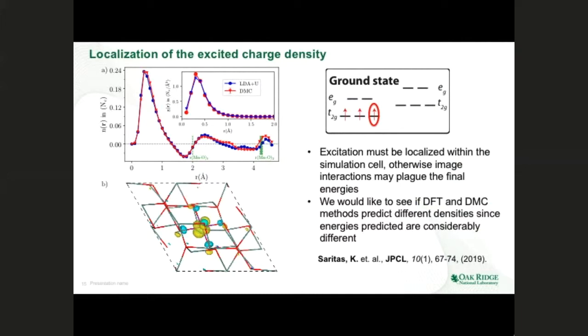And just a brief note about this material: when we started to simulate the excited state in this material, we needed to make sure that the excitation is well localized within the simulation cell. What we did in here was that this is the charge density from fixed node diffusion Monte Carlo calculations. We compared those charge densities with the LDA plus U charge densities that we used to prepare the trial wave function for these calculations. We're basically looking at the electron density of this electron, which flips to the t2g level of the minority spin channel. And we see that the charge densities don't really differ too much when we look at the DFT versus DMC calculations, and these are extrapolated DMC charge densities. It is important that the DMC is able to capture the missing correlation effects that would lead to accurate excitation energies in these compounds.